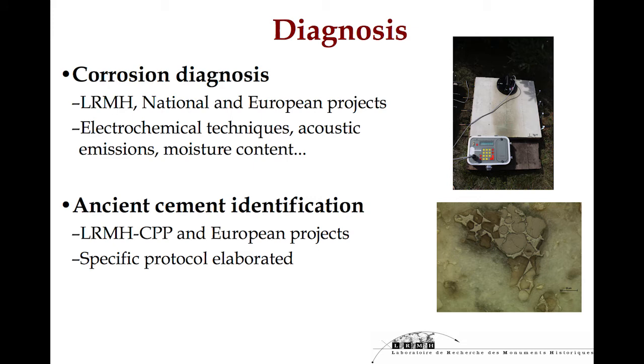Concerning the diagnosis and the corrosion diagnosis, we performed many projects, internal, national, and European projects, to work on electrochemical techniques, for example, to measure corrosion speed and resistivity. We worked on acoustic emissions to detect corrosion, and we worked too with techniques to measure moisture content. Concerning ancient cement identification, we performed internal projects and European projects, and we developed a specific protocol to identify ancient cement and particularly natural cements.